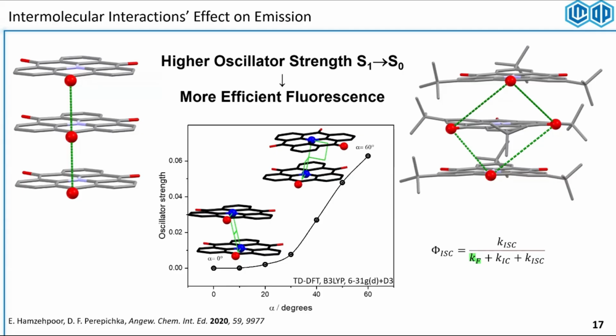It has the highest oscillator strength, meaning that when we excite the molecule to the singlet excited state, that singlet excited state that is generated is highly radiatively going back to the ground state to emit fluorescence light, whereas the non-rotated system, where it's reminiscent of the halogenated or non-halogenated derivative, has very low oscillator strength, meaning that when you excite it, it generates this singlet excited state, but it doesn't want to radiatively get back to the ground state.